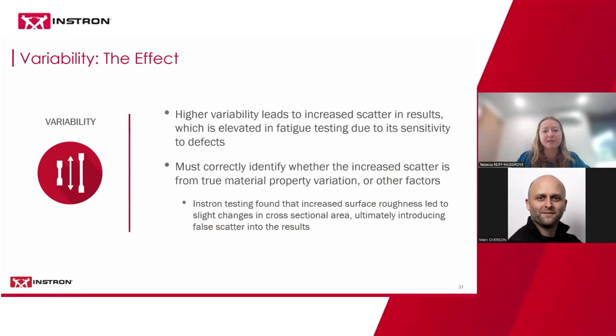So I just put a quick example here. I had a colleague do some testing internally, and they saw very high variation in their scatter in their results. And it actually turned out that it wasn't the material itself changing, it was the increased surface roughness that led to slight changes in cross-sectional area that kind of introduced false scattering to the results, as the incorrect stress was being calculated by using a blanket cross-sectional area across all of those. And that colleague will be discussing that more in some future blogs as well, so be on the lookout for those.